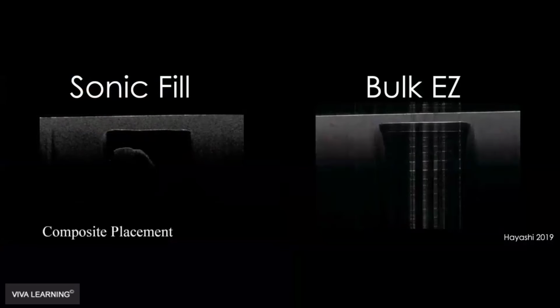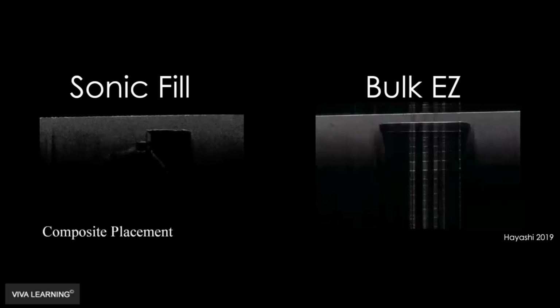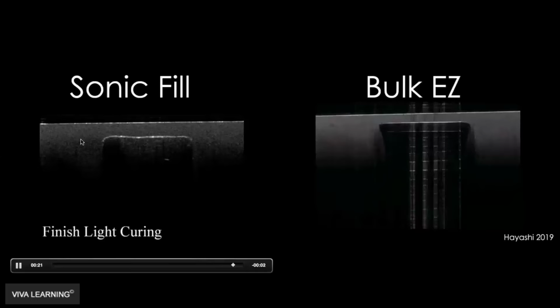This is data I wish we could do. This is my favorite test to measure shrinkage stress, and this is done at the University of Washington, where they've got this cool OCT, which is like an ultrasound for looking inside your restoration. What you see here is a simulated class 1, and you saw them pack a regular composite in there and then light cure it. After light curing, you'd see this little gap forming between the floor of the preparation and the restorative material.